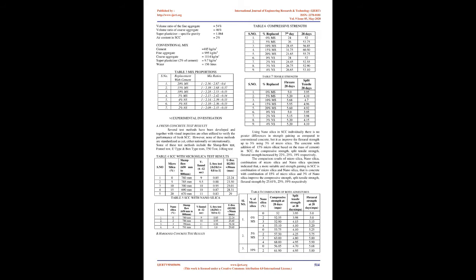It was noted that with 10 mm size aggregate and 52% fly ash in total powder, the mechanical properties were superior in standard SCC, while 16 mm size aggregate with 31% fly ash in total powder improved the properties of high-strength SCC. Size of aggregate was 10 mm for standard self-compacting concrete, M30, while it is 16 mm for high-strength self-compacting concrete, M70, though all other sizes were tried.